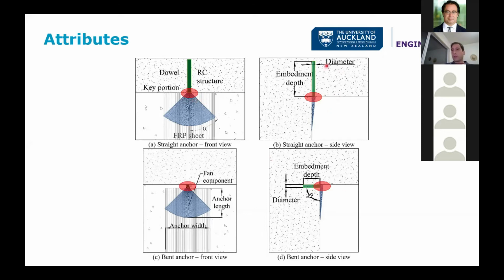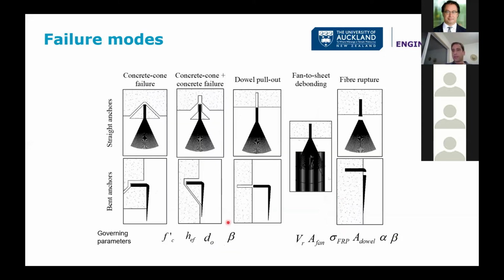Now, in addition to the diameter and the embedment depth of the dowel, we have the fan dimensions and the insertion angle beta. So all of these parameters here at the bottom will determine the failure mode. This is how I started my PhD, to look at the different failure modes that we can observe in FRP anchors. On the left-hand side, these 6 in here, we have concrete-related failure modes for straight anchors at the top, bent anchors at the bottom, and the governing parameters, which are the strength of the concrete, the depth of the dowel, the diameter, and the insertion angle beta there.